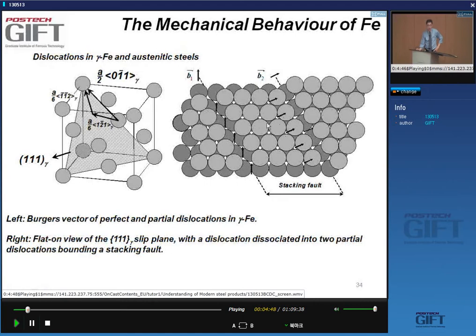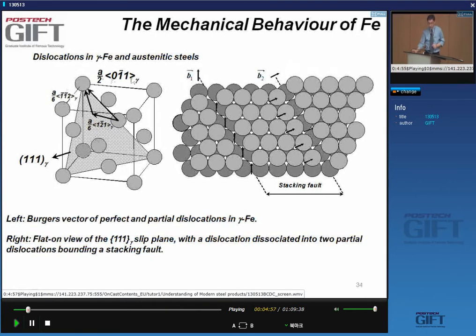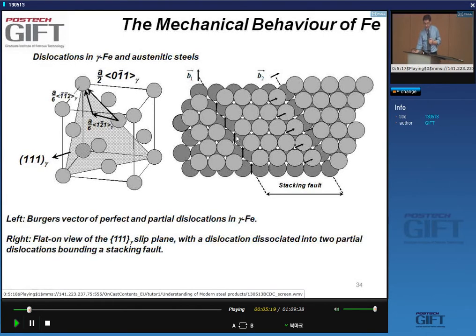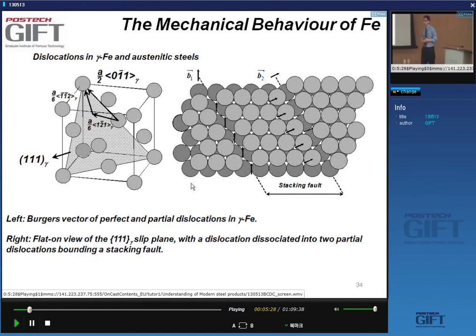In FCC, the glide planes are always 1-1-1 planes and the Burgers vectors are A/2 [0-1-1]. The core structure shows two partial dislocations whose Burgers vectors combine to form the full A/2 [0-1-1] dislocation. The Burgers vector of the partials is A/6 [1-1-2]. Between these two partial dislocations there is a stacking fault, which has far-reaching consequences for dislocation behavior in austenitic stainless steels.